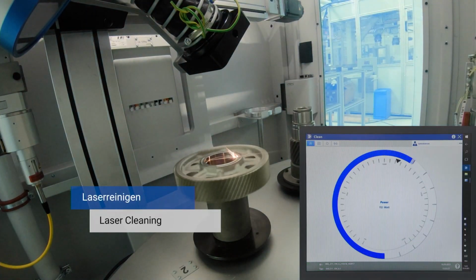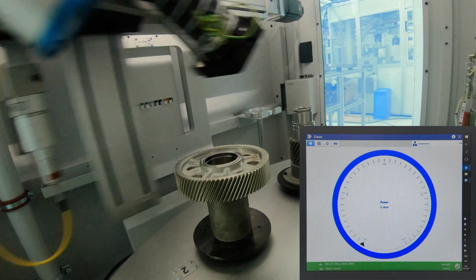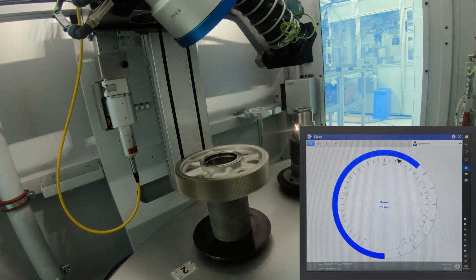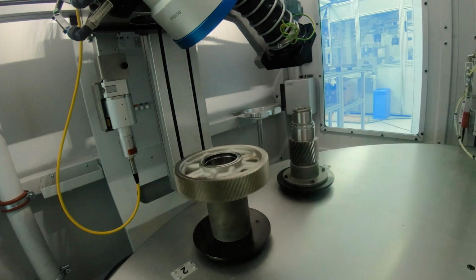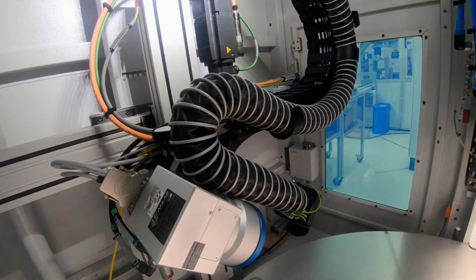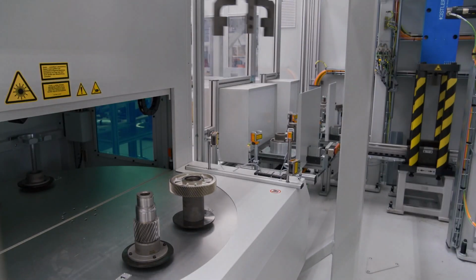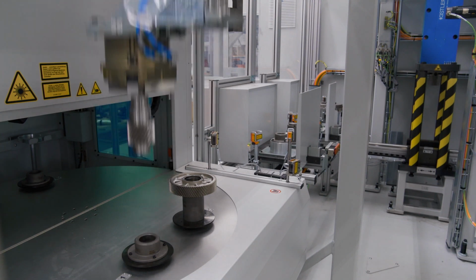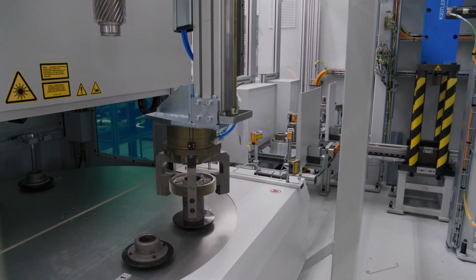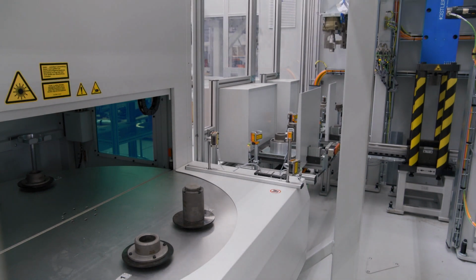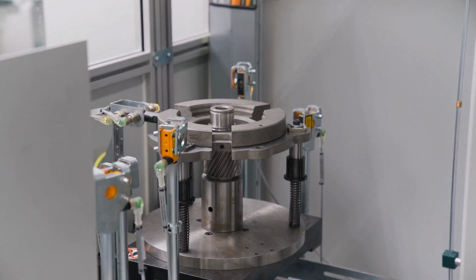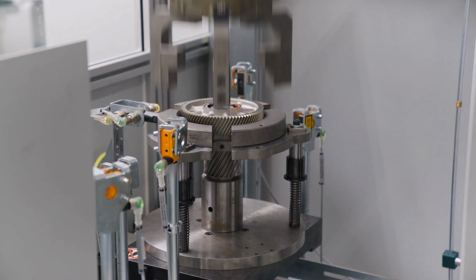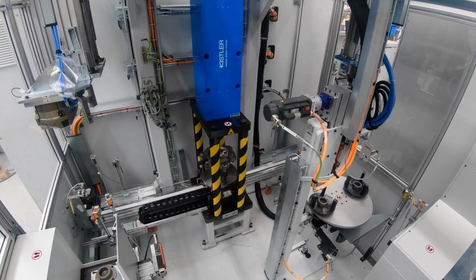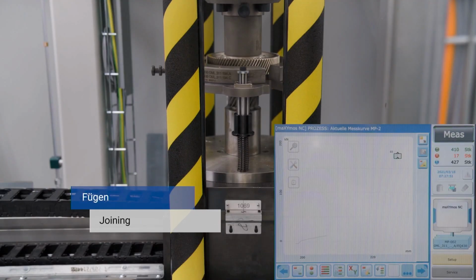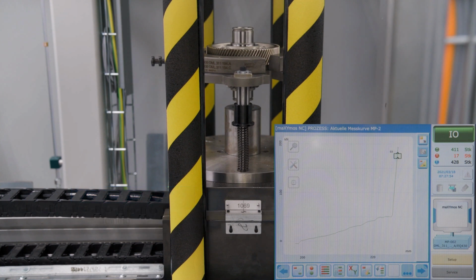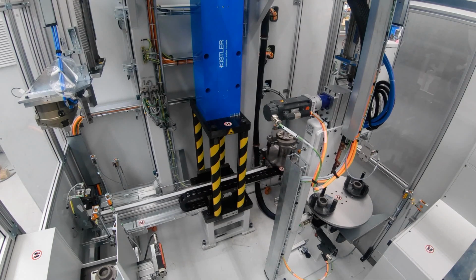So I have now received another question. Why do the parts still need to be cleaned before welding? They already come clean from pre-machining. That is not necessarily true, because from the pre-machining there might still be some residuals, for example from coolants or other fluids on the part. And if you have those organic substances on the part, then that's a high risk for cracking of the weld seam later. So that is definitely recommended, and let's say, for example, in differential welding, 90% of inquiries have this specification that laser cleaning must be done.